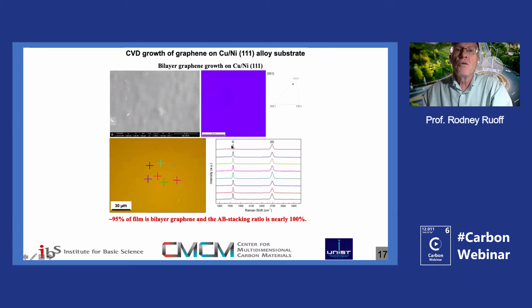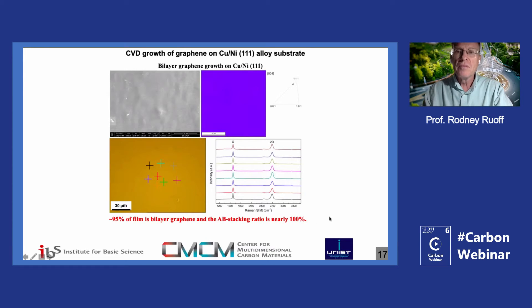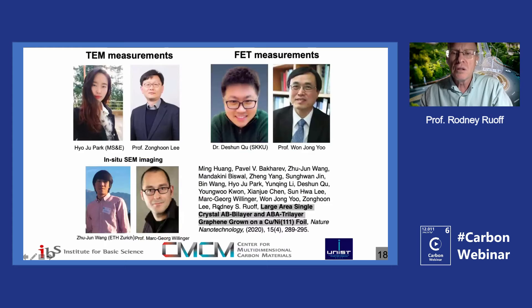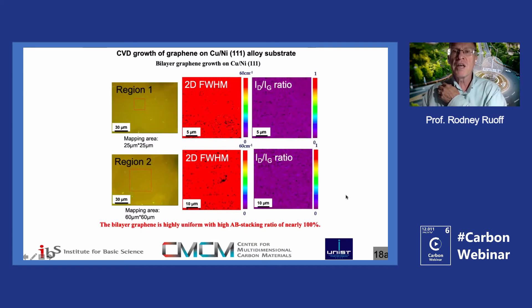By ramping up the nickel concentration to around 16 to 20 atomic percent in a parametric study, Ming found conditions where almost all of the film formed was AB-stacked bilayer graphene. Changing composition closer to 20% also yielded about 60% ABA trilayer graphene. Raman maps confirmed very high quality in all cases.